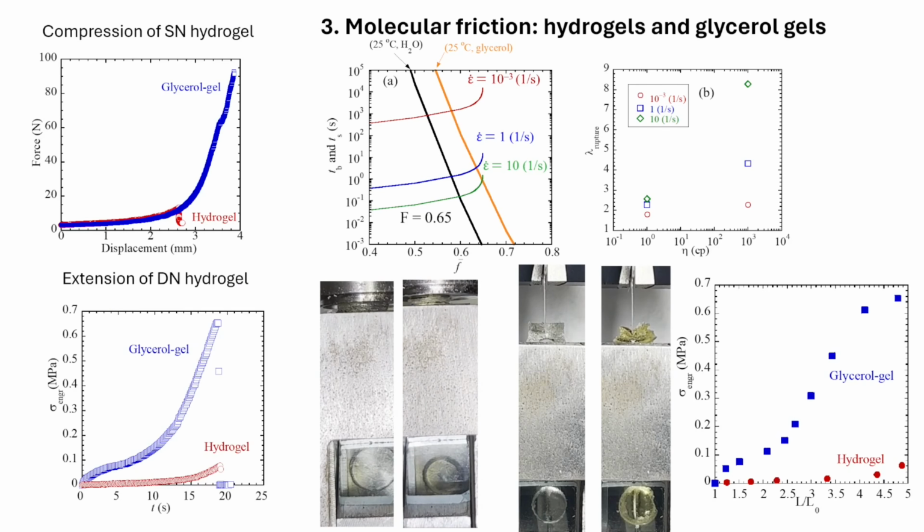This is a double network. The red is the network with water made in it. Very weak. Upon exchange to glycerol, my only interpretation I can have is this glycerol made the first sacrificial network strong enough, it doesn't collapse. That's the only thing I can do. That's it, I'm done.